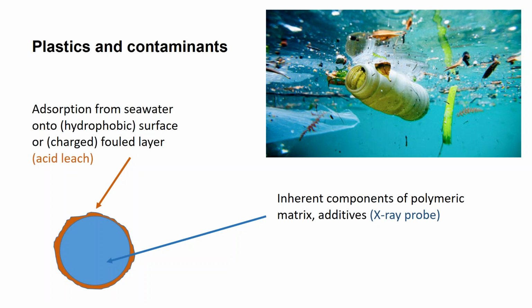Okay, so what about plastics and contaminants in the oceans? Well, we've talked about absorption from seawater, of the metals, for example, or any other organic contaminants that can stick onto the surface of the plastic, and we can look at this with an acid leach. But from what we've talked about on the previous slides, it's clear that many plastics have additives in the matrix. And the only way of really establishing what's in here is to use some technology that can probe non-destructively into the internal matrix of the polymer. And for that, we normally use an X-ray probe, like X-ray fluorescence.